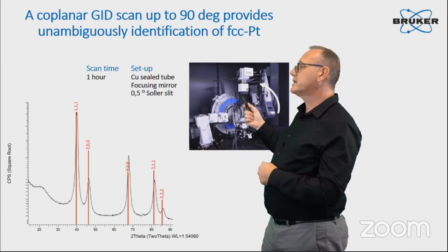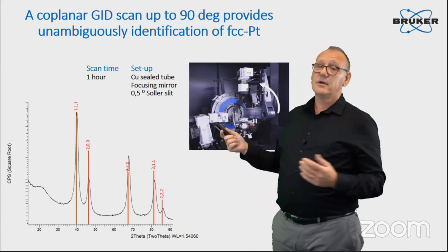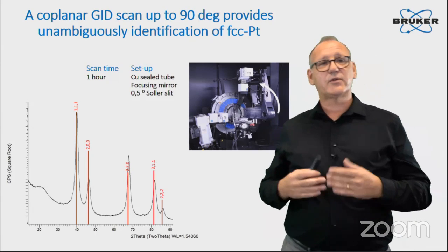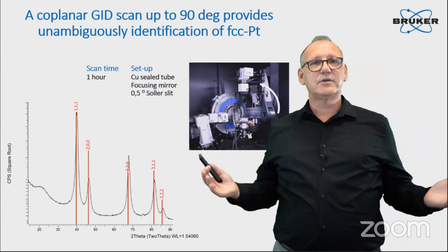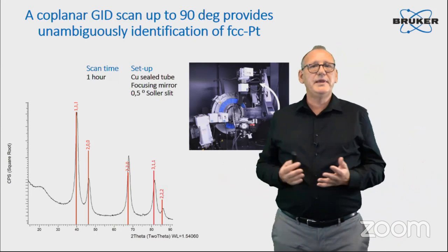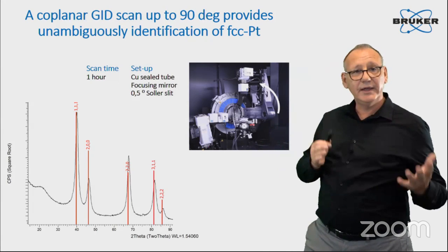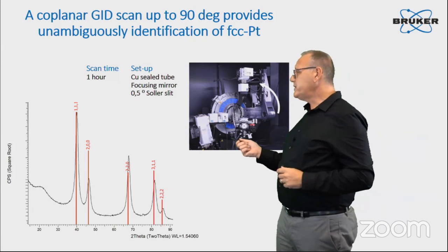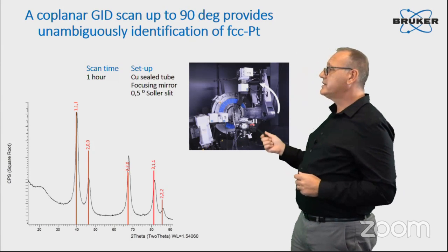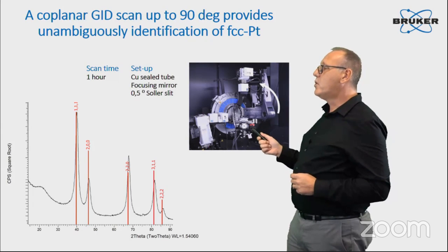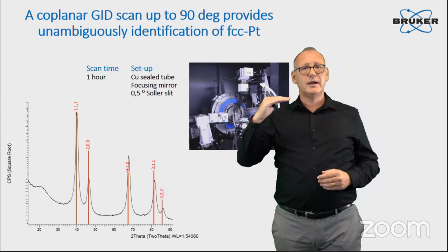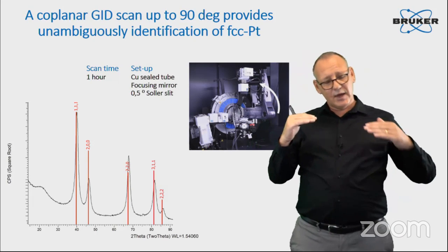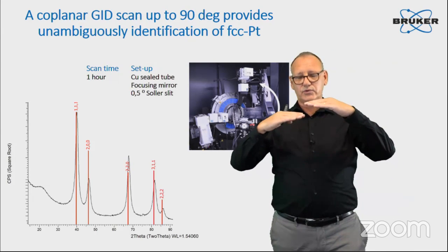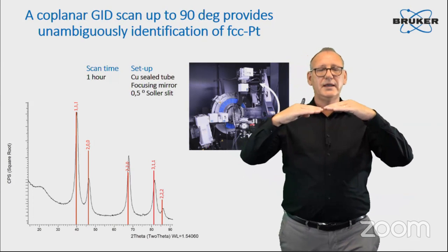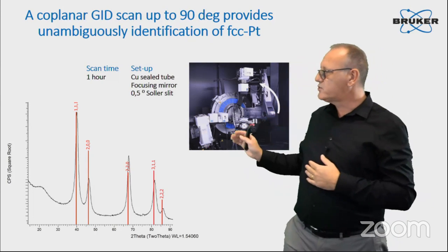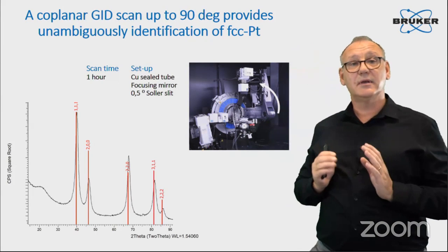And we have a pretty large acceptance of the Soller because from a nano-sized layer, we don't expect grain sizes which are going to be so big. So intrinsically, the peaks are broad. So again, better favor intensity than resolution. What we see in the center here also is a set of alignment drives. The most important one is actually the motorized height alignment. If you have a very grazing incident angle and you want to hit the surface, you have to very precisely adjust the sample height. So a Z drive for this kind of analysis is very important.